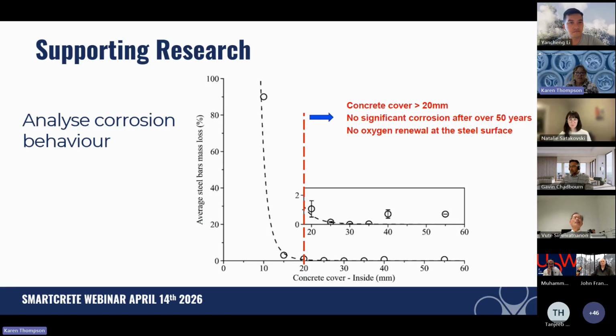Other supporting research it's covering is that the corrosion behaviour of steel in concrete pipes is unique. It suggests that corrosion products forming quickly at the crack tip create a barrier at the steel surface, limiting access for oxygen and humidity to the sound steel. As a result, active steel corrosion stops. In this case, oxide formation does not lead to any additional concrete cracking, as there is enough room for the rust expansion within the crack. Moreover, the loss of mass required to heal the crack tip is marginal. As a result, the early corrosion does not affect the service life of the structure.